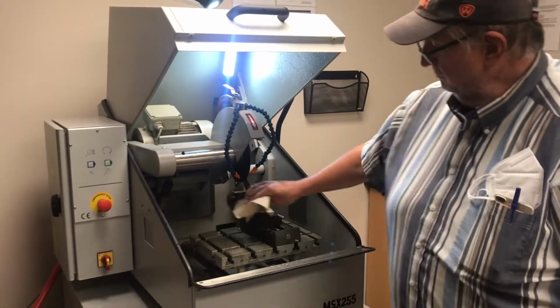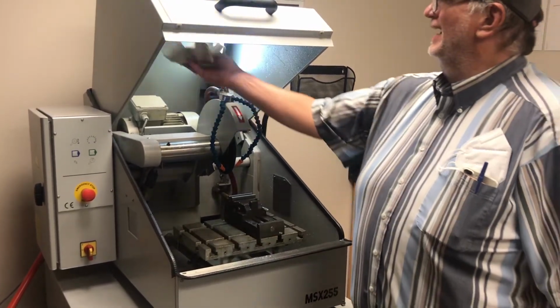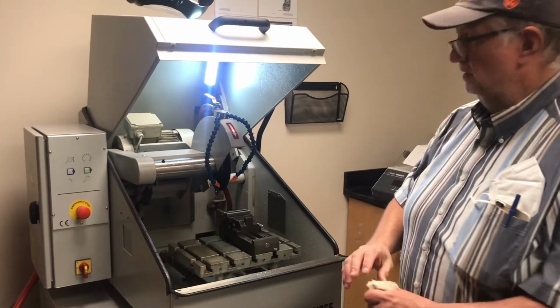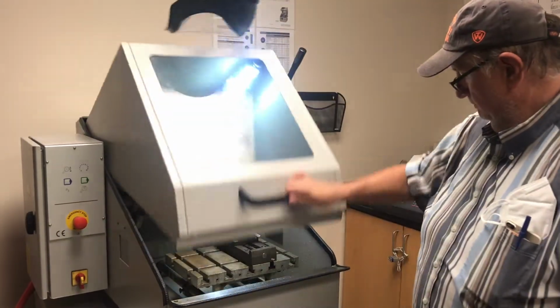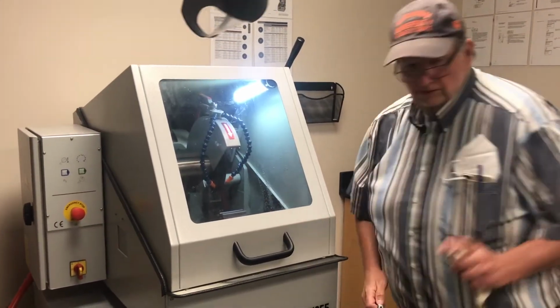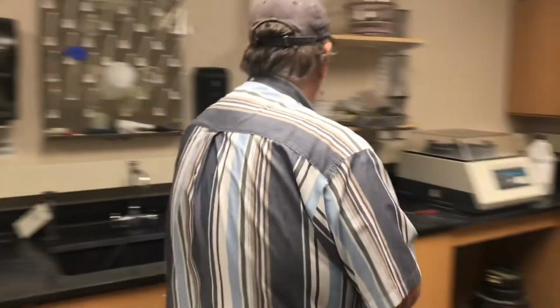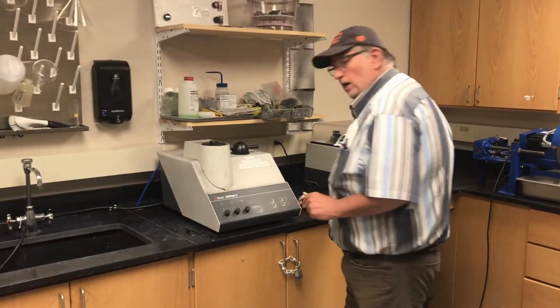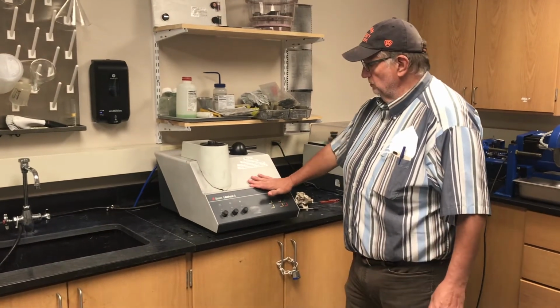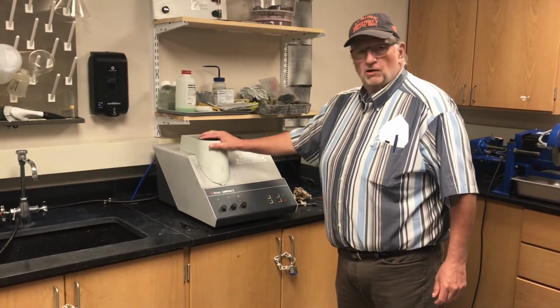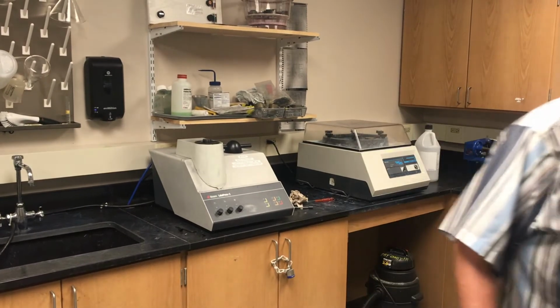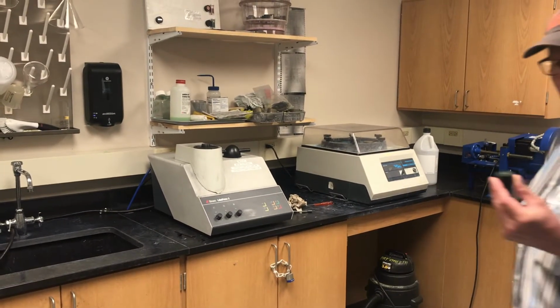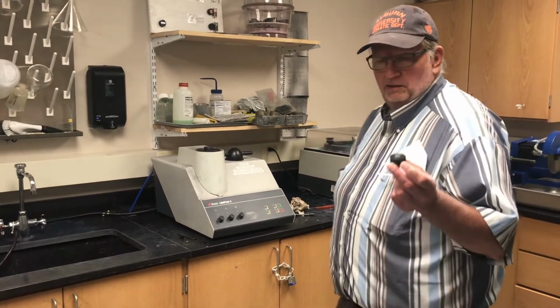take your paper towel, wipe off the stage, the bottom of the chamber near the cutting area, and the glass inside the hood. And then you're done. The next step, take the sample that you cut, bring it over to the Struers LevelPress 3. This is what's called a hot mount. The hot mount will produce a metallographic sample similar to this one.